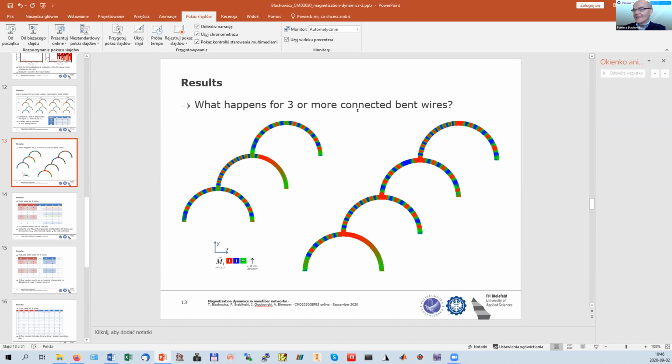From our technical host, David: are the fibers like cylindrical wires or squared stripes? And how would the cross-section modify your results? Absolutely, it will modify it. We performed different types of simulation with basically 3 types of cross-sections. Here there is a rectangle, but also a normal circular one, and also an oval, a little bit cut oval. This cross-section was a little bit similar to a real technological deposited fiber on the substrate. Absolutely, the results depend on the cross-section.